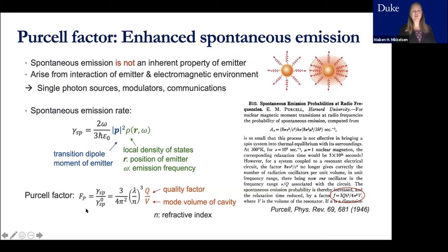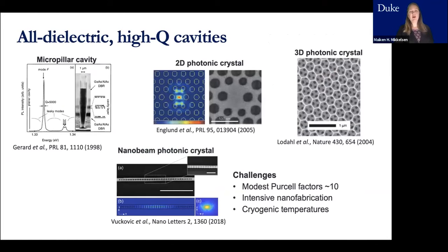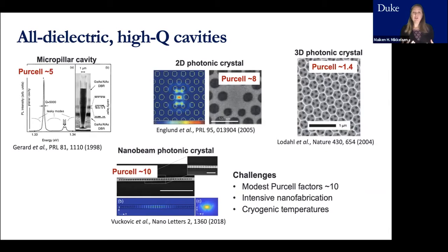The change in spontaneous emission rate is proportional to the quality factor of the cavity and inversely proportional to the mode volume. So these are the two knobs that are traditionally used to modify the spontaneous emission rate. A lot of work has been done in this area, originally using all-dielectric high-Q cavities, very beautiful work using micropillar cavities, 2D and 3D photonic crystal structures, and often at cryogenic temperatures. These are very tricky to fabricate, requiring a lot of hard work, and some of the highest Purcell factors were around a factor of 10 in this case.